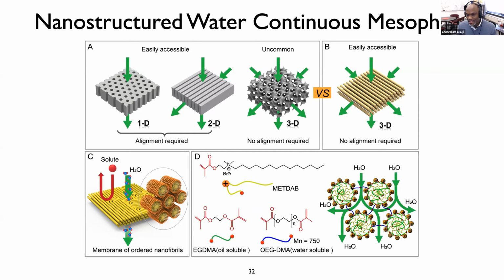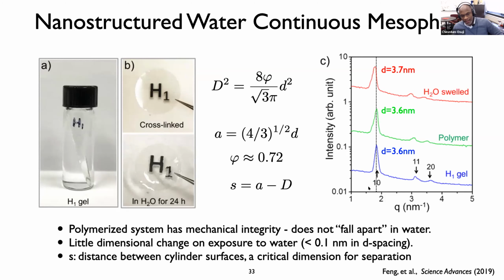Secondly, there's a finite density of molecular crosslinks that exist between the polymerized cylinders. And what we did, of course, was to augment that by the deliberate addition of, in this case, oligoethylene glycol dimethacrylate, which anchors itself inside of the cylinders and bridges the aqueous phase to make sure that there's good mechanical integrity in the system. So our advance here really was the demonstration that these hexagonally packed mesophases could be used to create materials suitable for nanofiltration, and the identification of compositions of matter that permitted rigorous retention of the structure of that mesophase throughout the processing associated with the formation of a membrane.